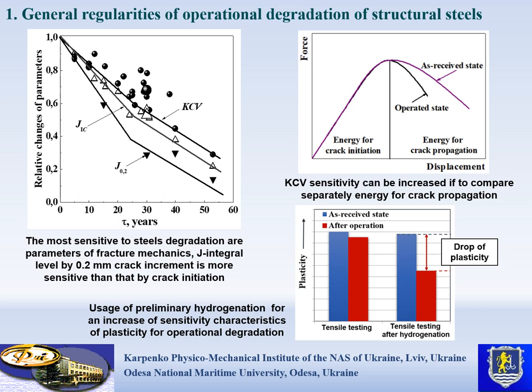Concerning the impact strength test, we divided total energy into two items: energy for crack initiation and energy for crack propagation. The scheme shows that energy for crack initiation is not sensitive to degradation, only the energy for crack propagation. Supporting the preliminary result with J-integral evaluation, the crack growth resistance is the most sensitive to degradation. It means that KCV sensitivity can be increased if we compare separately energy for crack propagation for unoperated and operated states of steel.